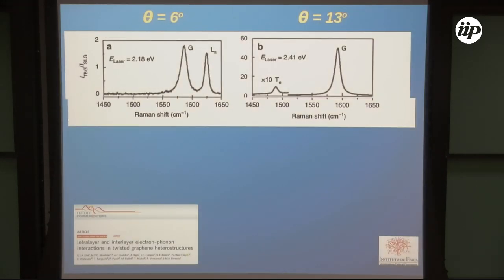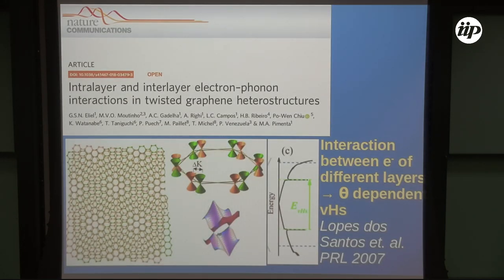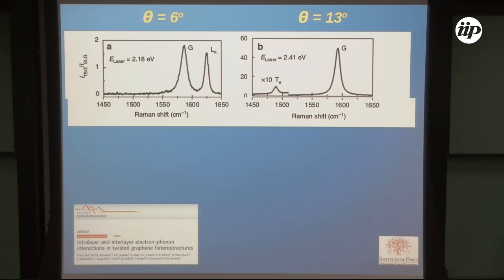Okay, so what Eliel did, he did several Raman measurements in these samples. So this is the G band. This is for one angle, another angle, and there are other Raman peaks that only appear if you have twisted bilayer graphene. They are clearly a fingerprint of the twisting. Okay, this was already known. There were several papers about that. I think that what we did, we could give a very clear explanation of the origin of those peaks that appear when you have a given angle.